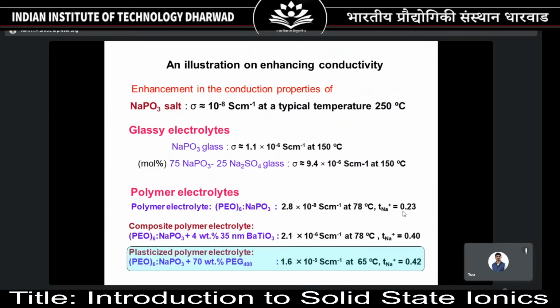So to summarize, I am giving this example which I have explained. We had a sodium phosphate salt which was showing conductivity of the order of 10 to the power -8 Siemens per centimeter at 250 degrees Celsius. When it became glass, that means you melt it and quench it, you get a glass which has shown conductivity of the order of 10 to the power -6 Siemens per centimeter at 150 degrees Celsius. When you added dopant, it has further enhanced by one order. That is in the case of amorphous materials.